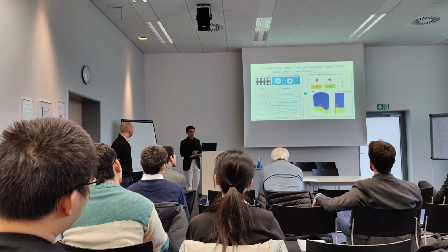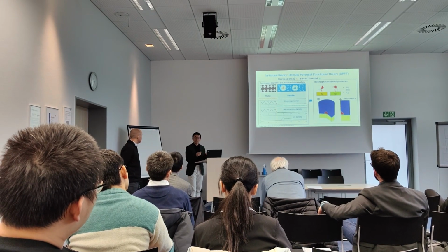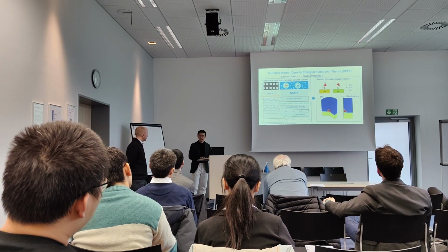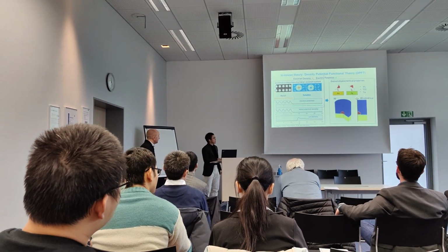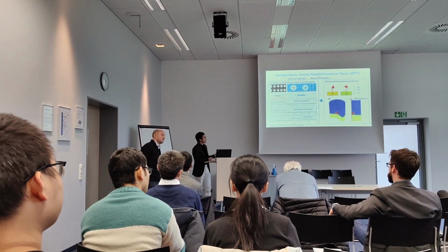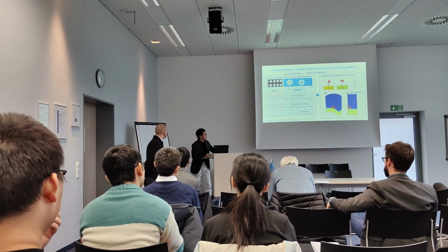So we first calibrate our model parameters to reproduce these three properties for a homogeneous planar electrode. Gold and silver have well-defined, reproducible data for the differential capacitance curve, but platinum and carbon do not. So we first chose gold and silver as a model system, and later we will expand this methodology to account for platinum and carbon chemistry.